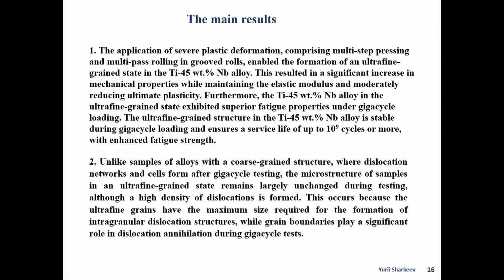First, the application of severe plastic deformation comprising multi-step pressing and multi-pass rolling in grooved rolls enabled the formation of an ultrafine grain state in the titanium niobium alloy. This resulted in a significant increase in mechanical properties while maintaining the elastic modulus and moderately reducing ultimate plasticity. Furthermore, the titanium niobium alloy in the ultrafine grain state exhibited superior fatigue properties under gigacycle loading. The ultrafine grain structure in the titanium niobium alloy is stable during gigacycle loading and ensures a service life up to 10 to the power 9 cycles or more with enhanced fatigue strength.